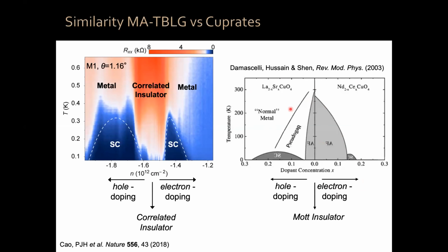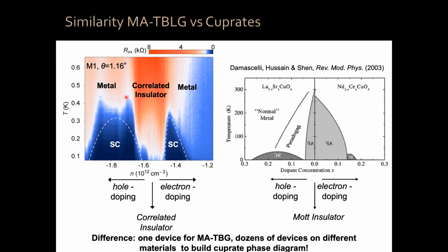Experimentally, to build this phase diagram, you need to grow hundreds of crystals, each with different chemistry, often each with different elements and compositions, because you cannot grow all materials or dope them for holes, for electrons, and in all the doping ranges. So to build this phase diagram took thousands of growths by many crystal growers, growing different material classes with different dopings. Here, this phase diagram is in a single device, realized electrostatically, and it takes us a few seconds to go from here to here and measure this entire thing. It takes only a few hours. So that's a big difference between these 2 systems. There are other differences. The analogy only goes so far.